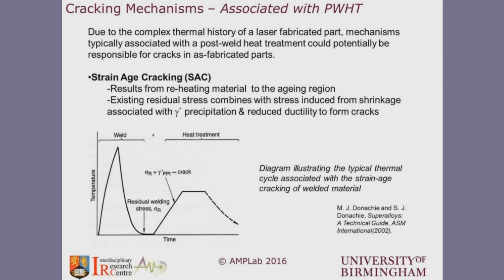In simple terms, typically you will build a material by additive manufacturing or welding it, and when you weld it or build it, it doesn't show any cracks. But then you expose that material to a stress relief heat treatment, and it actually cracks within the post-weld heat treatment process. That's what's known as strain age cracking, or post-weld heat treated cracking.